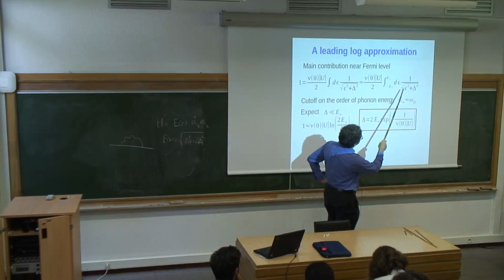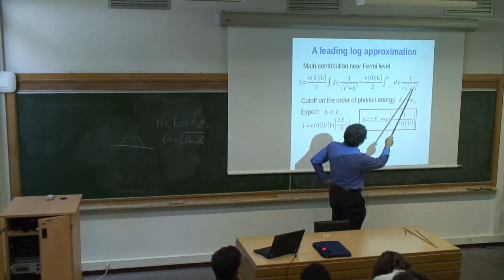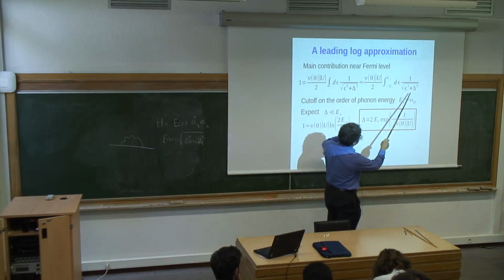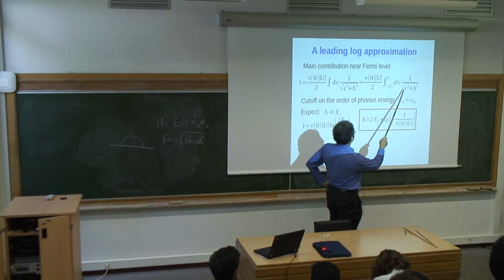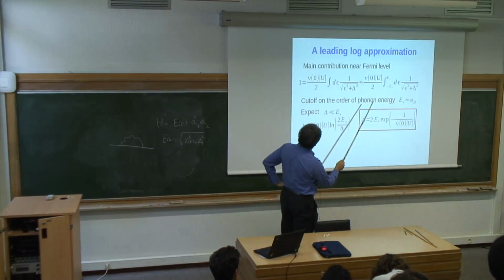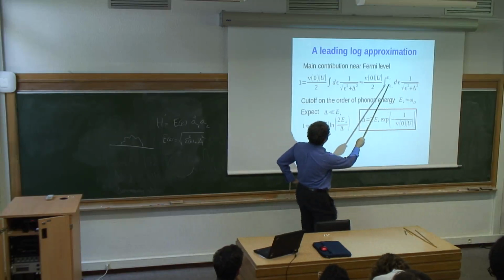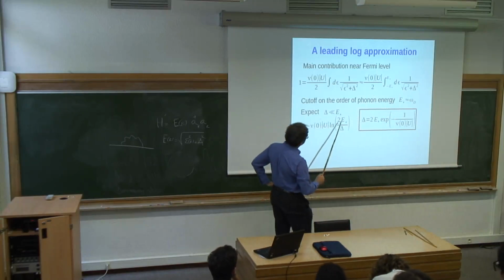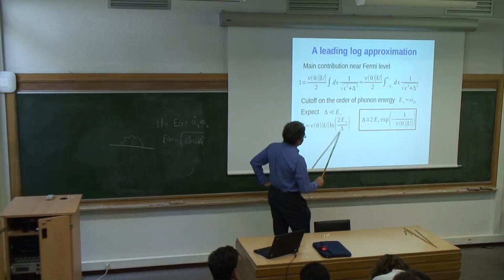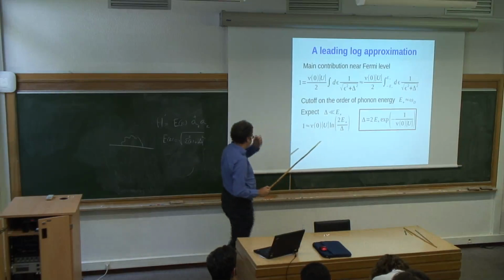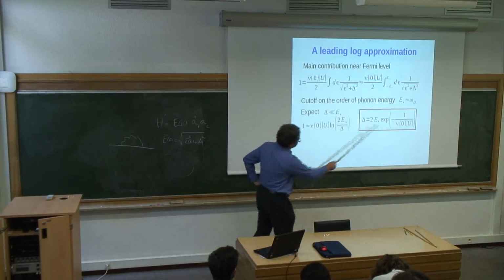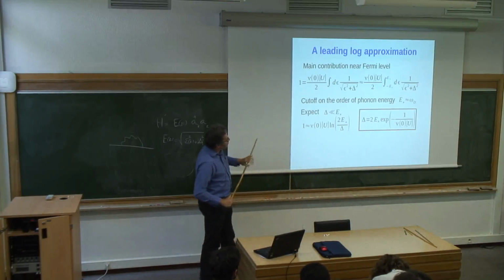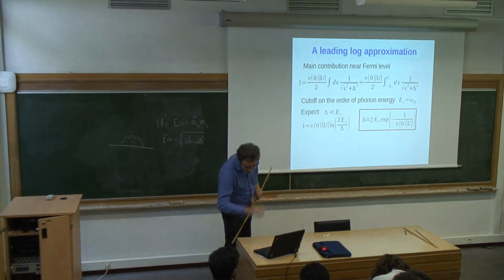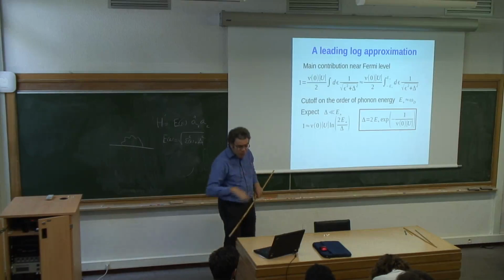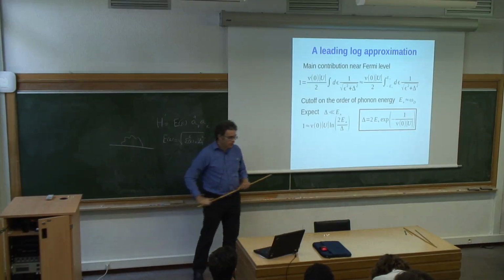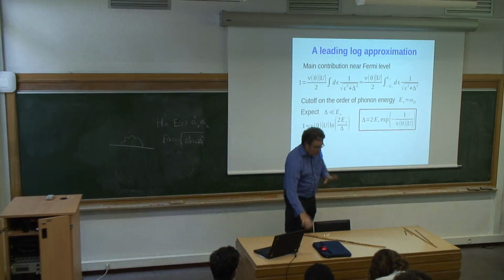And this log would be divergent in the absence of delta, but delta will cut the divergence at zero energy, zero epsilon, and so it will take the form of log of delta appearing as an infrared cutoff, and that will lead, solving this for delta, will lead to this exponential dependence. So that's all.